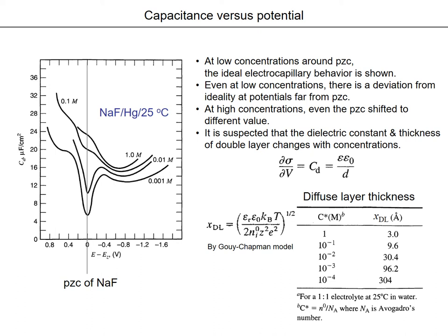Another real result is the capacitance versus potential curves. Of course, it comes from the capillary curves. In this case, sodium fluoride is used on the mercury electrode at 25 degrees Celsius. Also, the concentrations are changed from 0.001 molar to 1.0 molar.